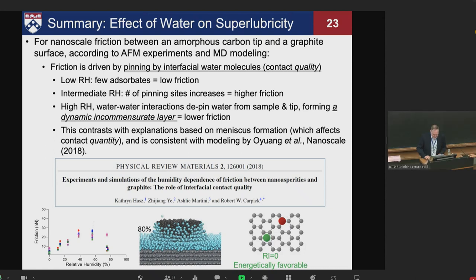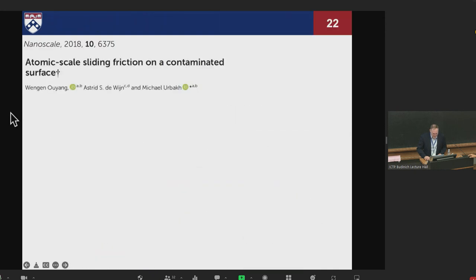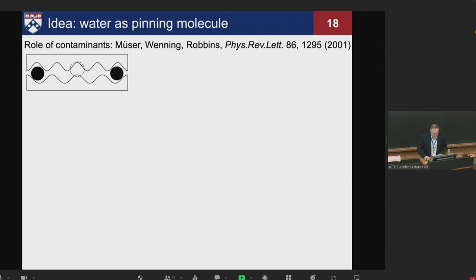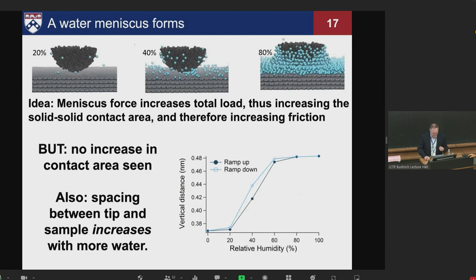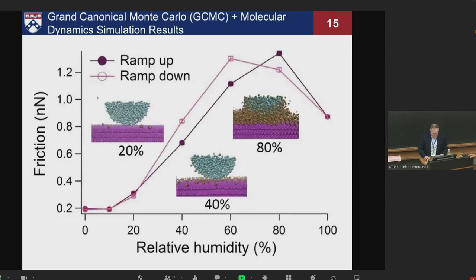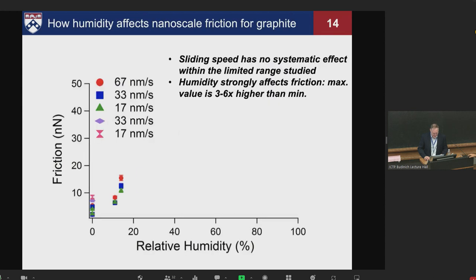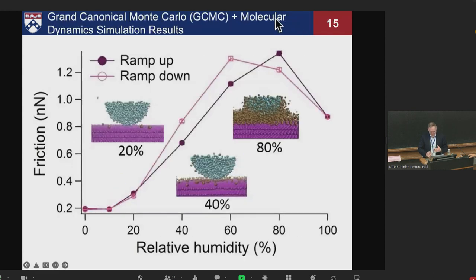So the way it was done in the molecular dynamics simulations was using the LAMMPS framework for running the simulation, and the potential was the so-called mW molecular water potential, which we cite in the paper. And it's a grand canonical Monte Carlo simulation. What that means is you allow the number of water molecules to vary and reach a steady state, an equilibrium value, at each of the different humidities. And that's a fairly well-established method. Ashley will be here this afternoon and can answer more about that. We also have the details in the paper. But essentially, it's all through molecular dynamics.